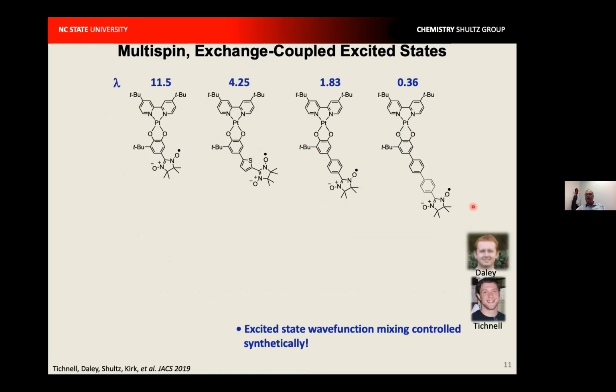So my students, David Daly and Chris Tichnell, made a series of these complexes where, again, by knowledge of the exchange coupling in the corresponding zinc complexes, we could calculate the D-trip D-sing mixing parameter lambda, which varies as shown here. And then with ultra-fast transient absorption spectroscopy, they measured the lifetimes of the D-trip states of these molecules. And as you can see, they varied from 252 picoseconds when the mixing parameter was relatively large, up to just over 1 nanosecond when the D-sing D-trip mixing parameter was quite weak.